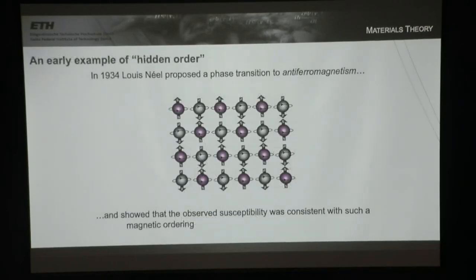Of course now we know, in fact, very soon after that experiment was done, Néel proposed that there was a phase transition to a magnetic order, which we now call antiferromagnetism, that the magnetic moments were ordered. These little arrows are representing the magnetic dipole moments. These would be spins in the case of manganese oxide. But there's no overall magnetization. There's an equal number of up magnetic moments as down magnetic moments. And so this explained how there could be a cusp in susceptibility, and also that there was no net magnetization to measure.